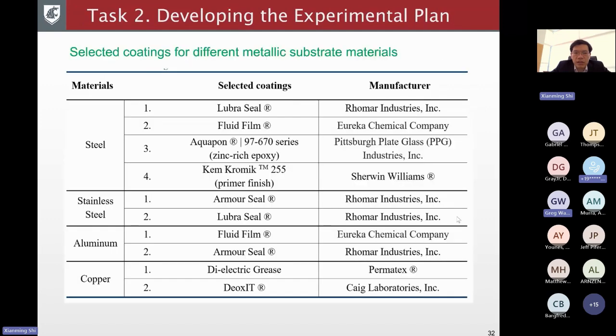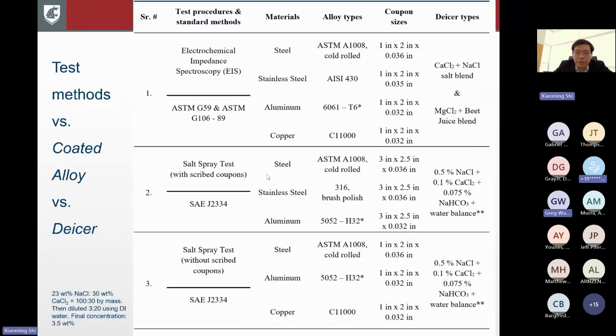So here is some more details. Again, if you look at this table, on the left is the column on materials. We had 4 different metal types: steel, which is basically carbon steel, and then stainless steel, aluminum, and copper. And then for each of them, we select several coatings. As you can see here, this was the list, and then we further finalized this based on consultation with the project panel. And then here's a more detailed table with different test methods as a function of the coating type, the metal alloy type, and then again the different deicers we used.